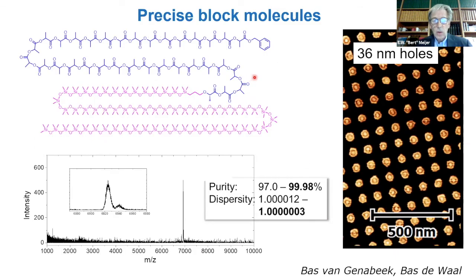And here you see the longest one we made. The lactic acid is racemic, and this is dimethyl siloxane. Much to our surprise, everyone has dimethyl siloxanes at home, but no one really made these discrete oligomers longer than about 6 or 8. And here you see that the dispersity is now 1.00000 something. And if you now fill these holes, I hope you appreciate that the regularity is much higher here than it was in the previous case. And it was work from Bas van Genabeek and Bas de Waal who synthesized these molecules.